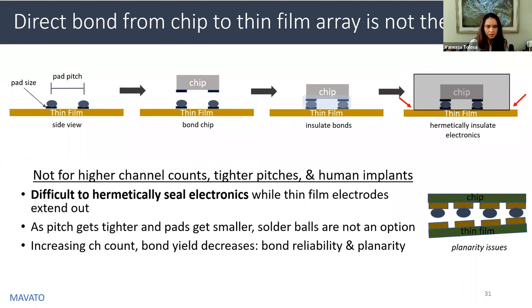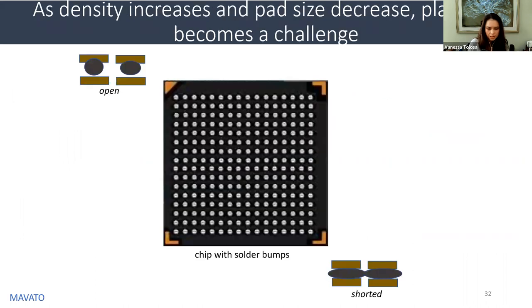And then the last point I have to make on this kind of design is the image on the bottom right. Another challenge with flip chip bonding as you go to higher channel counts and densities is planarity. Any warping of either of your pieces will cause a situation where you can't get 100% yield. Here's another view of that. You may be able to get a perfect connection in many of the areas, but if you push too much in one area, you get shorts, and then it lifts up on the other corner, and then you get opens. So it becomes really difficult to get high yield with this process as you get to these higher densities, smaller features, bigger pieces. In R&D, this isn't that big of a deal if your yield isn't perfect. But if you're trying to commercialize a product, this can be a deal breaker.